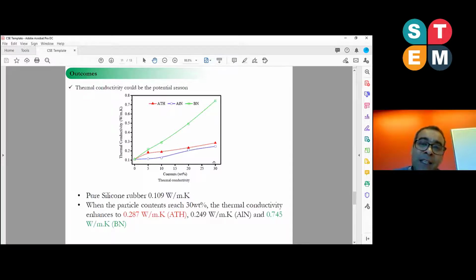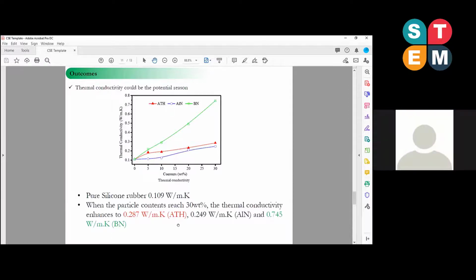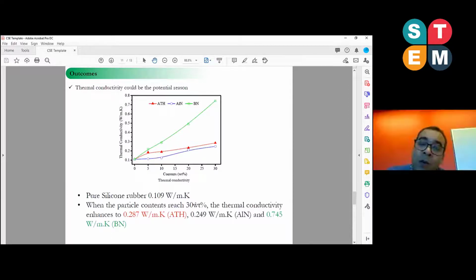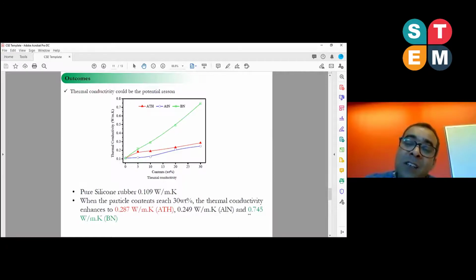and ATH and ALN, we can see a substantial increment in the BN-filled samples at 30%. Pure silicone has a very low thermal conductivity of 0.109. But when the particle content reaches around 30%, the thermal conductivity is enhanced to 0.287 in the case of ATH and 0.249 in the case of ALN, but with the BN it is substantially increased to 0.745.